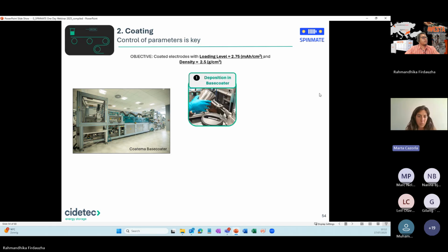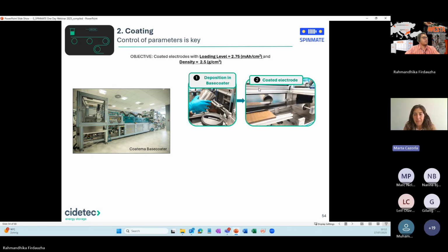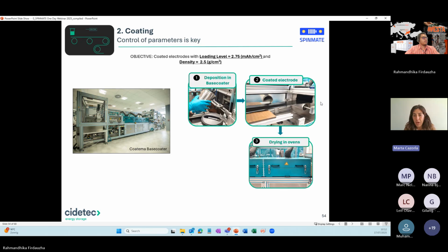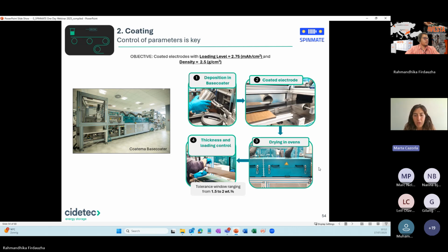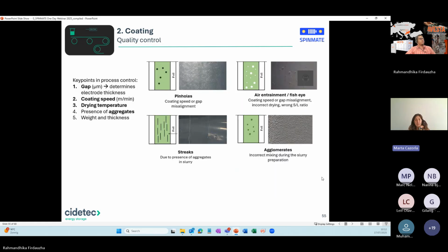So in Cidetec, we do it in this type of Coatema-based coaters. We deposit the slurry, and then we have the coated electrode, that is then dried at a certain temperature and speed, and then again all the time we measure the thickness and the loading control, having some tolerance windows. And this step is also important to see, because we can have many issues at this step. So it is important to control the gap, that is the space between the coater, which will actually define how thick and how fast our coating is being deposited.